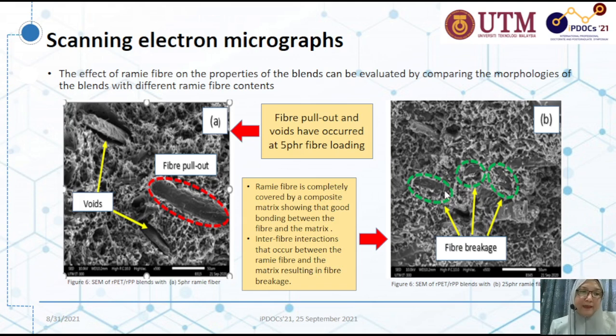So due to the impact test result, the recycled PET, recycled PP with 25 pHr ramie has the lowest value. This may be due to the interfiber interaction that occurs between the ramie fiber and the matrix, resulting in fiber breakage and blocking the effective stress transfer between the fiber and the matrix. The SEM image also showed that the ramie fiber has absorbed the applied energy, which results in fiber breakage.